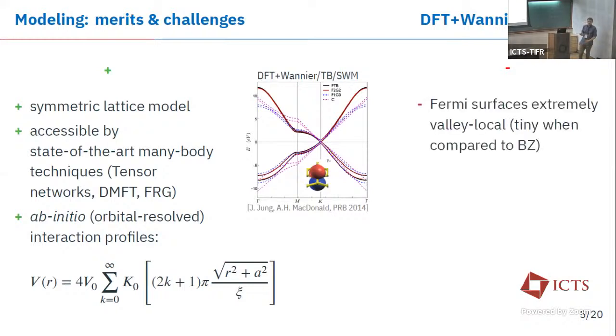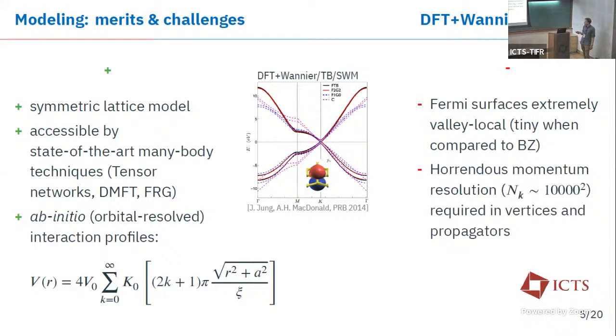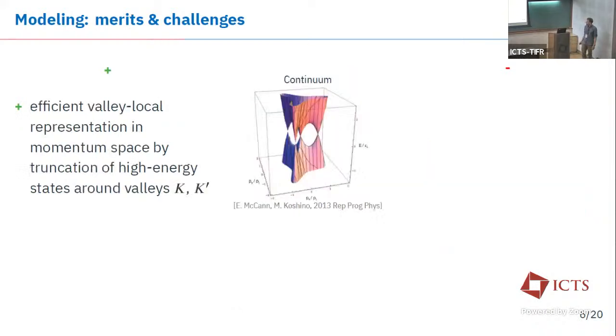On the other hand, which is what Julian already asked, and I only put up here, you have very tiny and valley localized Fermi surfaces, at least in those graphitic systems, which makes it hard to model the full Brillouin zone and also at the same time the Fermi surface. And this leads to the requirement of horrendous momentum resolutions for any quantity in simulations of the interacting problem. On the other hand, continuum models directly have a very efficient valley local representation in momentum space.